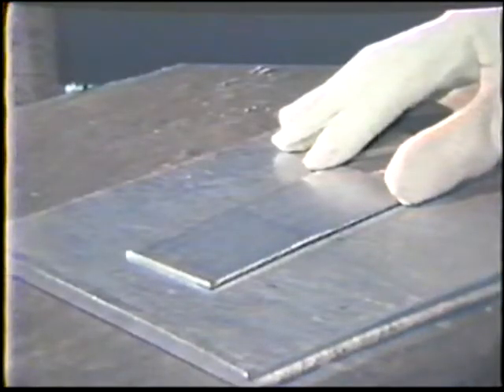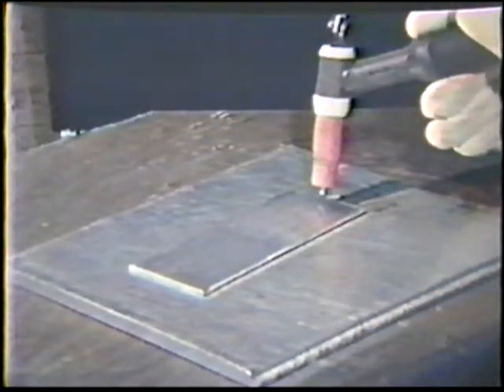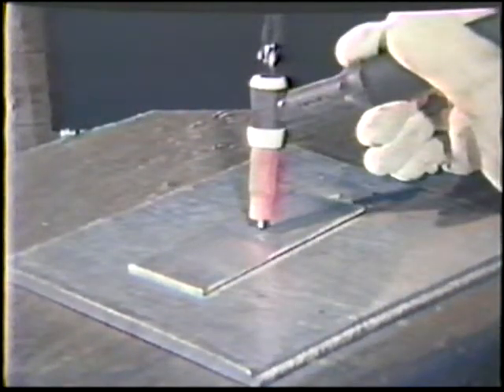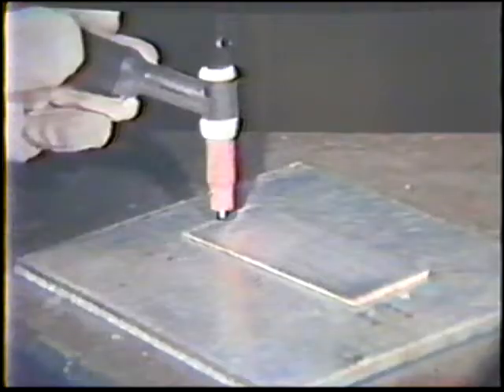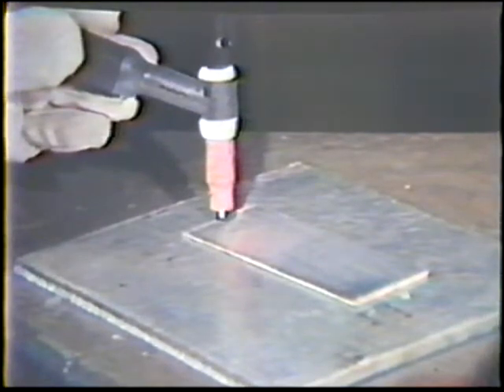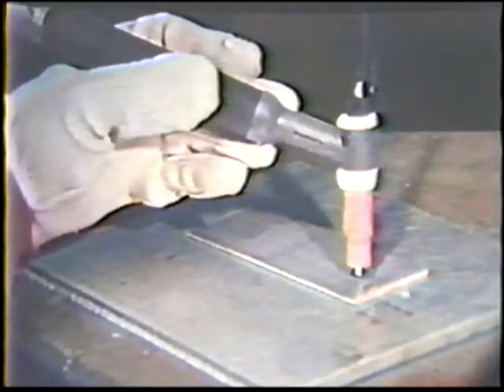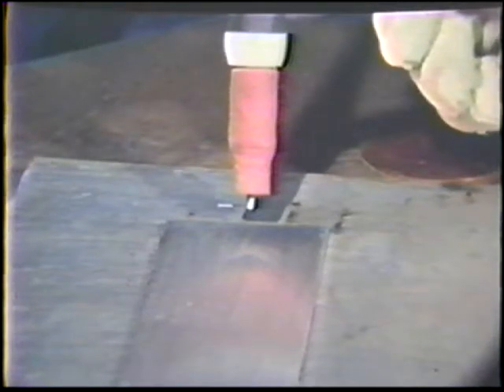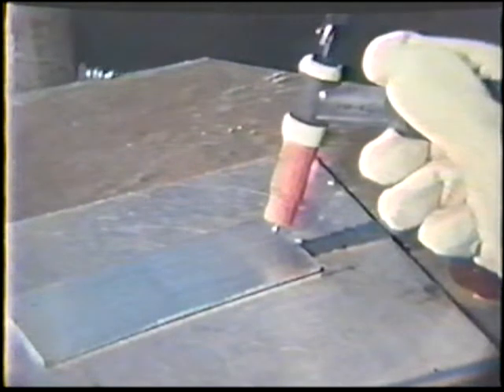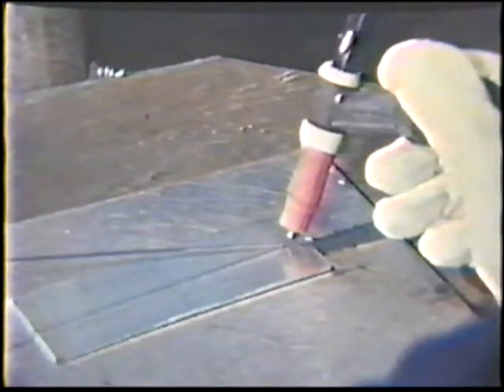Place the aluminum on the work table in the flat position. For a right-handed welder, position the torch at the right end of the joint. The torch is moved from right to left. For a left-handed welder, the torch is positioned at the left end of the joint and moved to the right. Hold the torch with a 90-degree work angle and a 20-degree push travel angle. The filler rod should be angled up from the plate 20 degrees with no side angle.